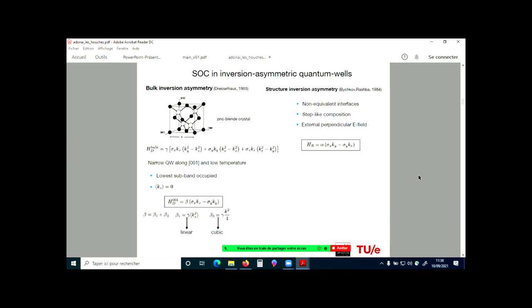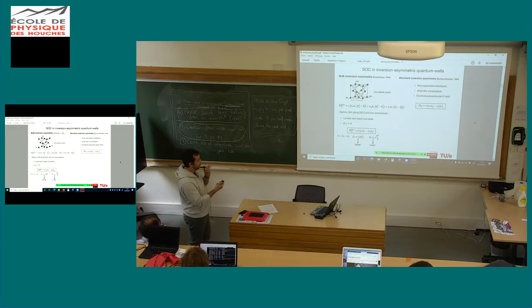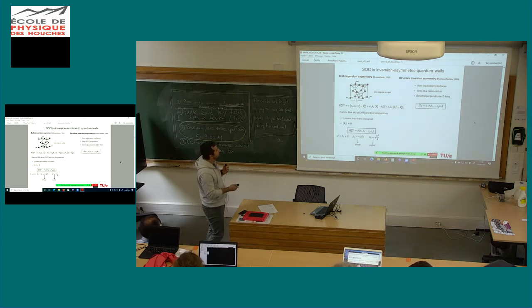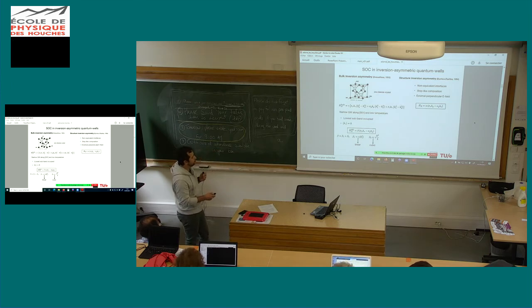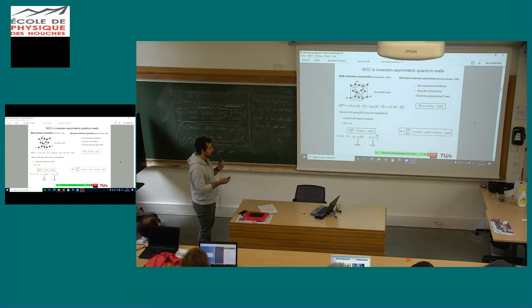The second one is the structure inversion asymmetry, also called Rashba spin-orbit coupling. It comes from the non-equivalent interfaces. If you break close to the surface, for instance, we can have a step-like composition in the system, and it's also tunable by an external electric field perpendicular to the quantum well. This is the expression, and this is actually my model. It's a very simple way to describe a conduction electron in this two-dimensional electron gas with spin-orbit coupling.